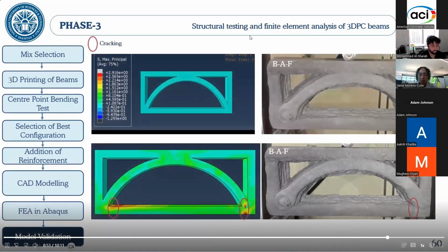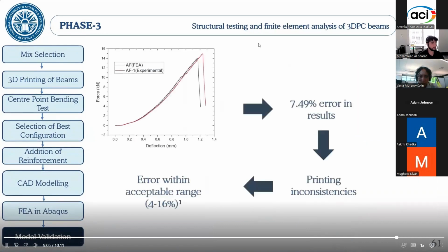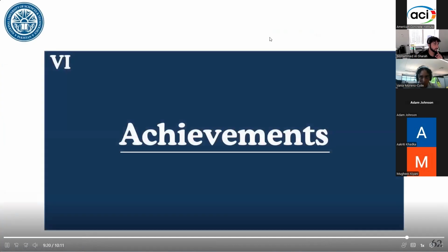Now, if you look at the experimental and the numerical results, we can see a high degree of similarity between the both, where the cracks occurring near the joints. Comparing the experimental and the FE results, we saw a 7.49% error in results, which can be attributed to the printing inconsistencies. However, this error was within the acceptable range as given in the literature.